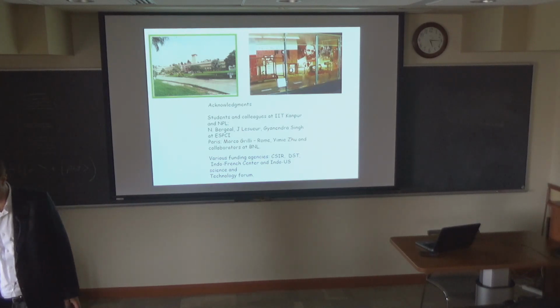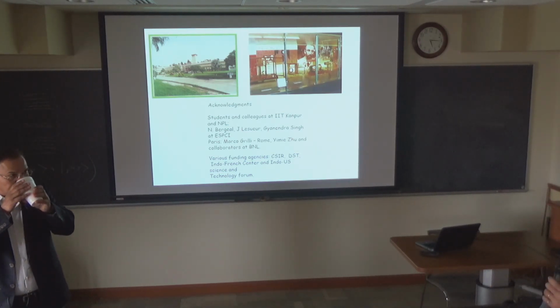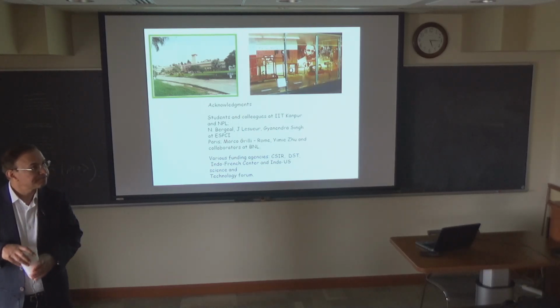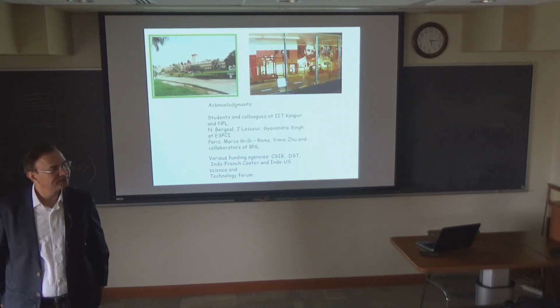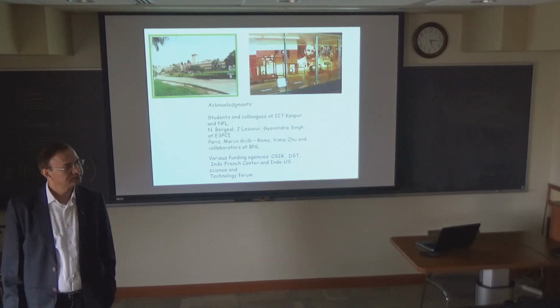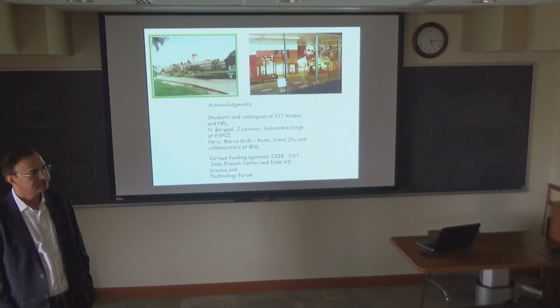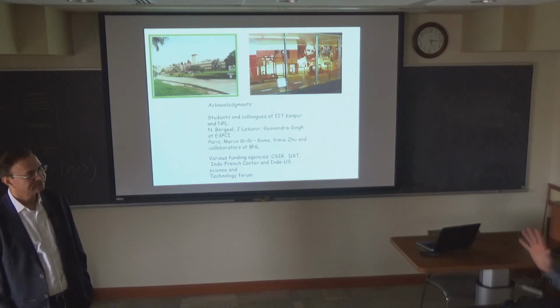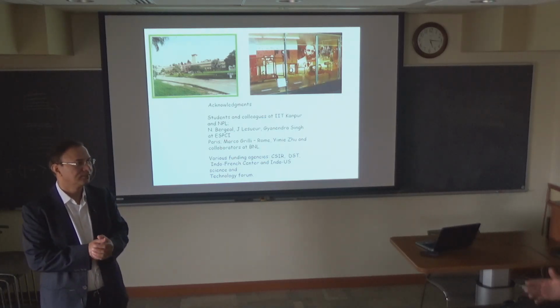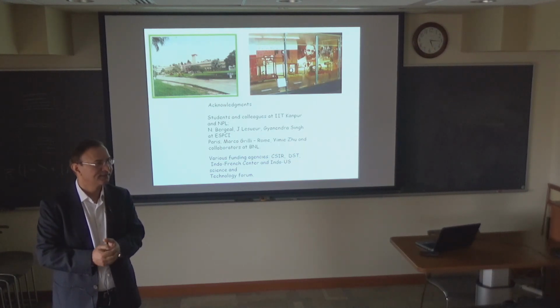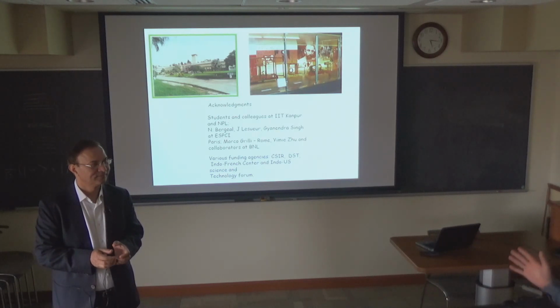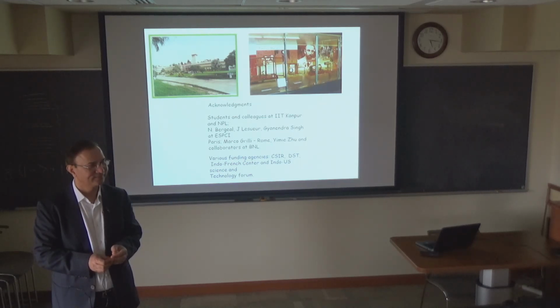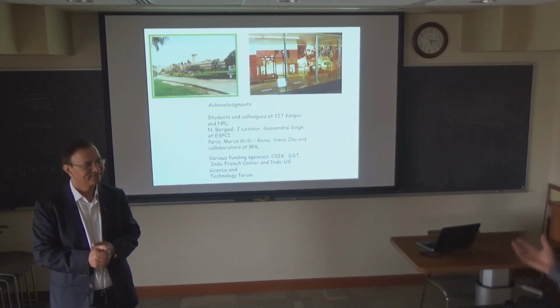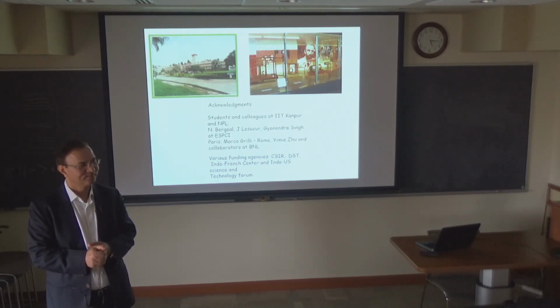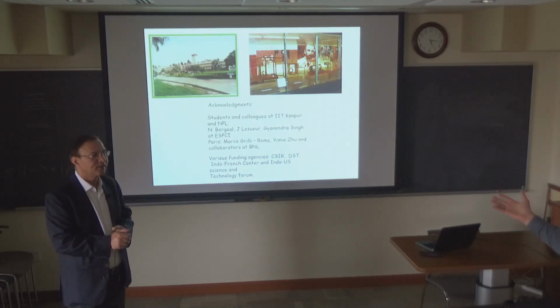I have a question. It is very interesting, these microwave measurements, with the interpretation of the Josephson junctions. You didn't mention anywhere in your talk anything about ferroelastic domains and what happens at low density. There's a lot of work on LAO/STO, which you just said is very similar to LTO/STO, showing that the transport is very anisotropic and even dominated by filamentary transport. So how does that affect your interpretation?